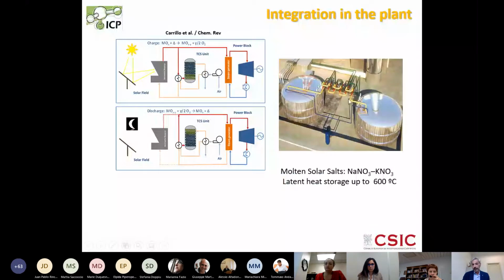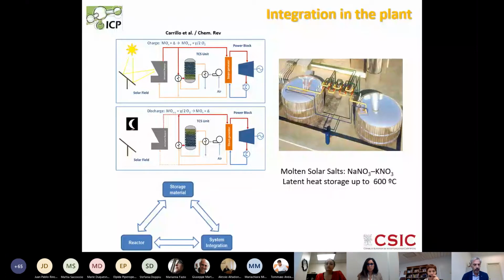This is an example of this huge reservoir of solar salt they are using in some of the plants right now. And these salts can be used at up to 600 degrees, probably a little bit less than that, because at higher temperatures, you start to decompose and you start to have problems. So as you can see, this technology in the plants is a combination of several elements. We need to store materials, that is the focus of today. But we also need a reactor that at the same time is a heat exchanger. We need a system integration in order to have a smooth operation of the whole system.